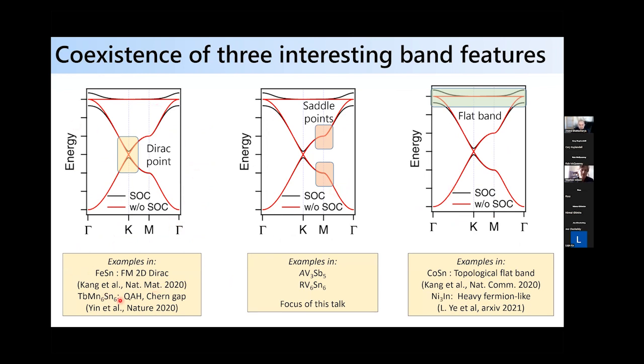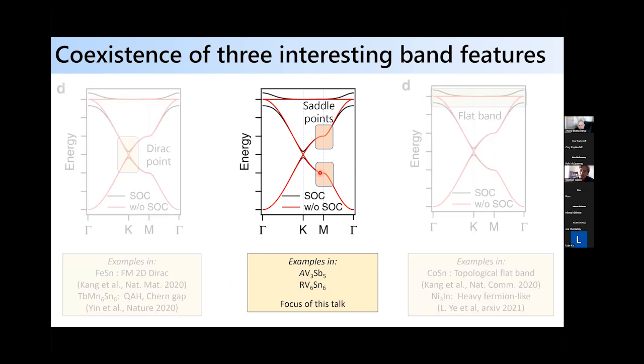So for instance, iron tin or these manganese-based 166 compounds exploit a lot of the phenomenology that comes from gapping out the Dirac points that are native to the kagome band structure. Joe Checkelsky's group has some beautiful recent work on Ni3In, looking at flat band physics, for instance, if you can tune the Fermi level towards the flat band in the kagome band structure. And these vanadium-based 166 compounds I was showing you nominally have fillings which are near the saddle points in their Fermi level. So this spurred some of our initial interest in these materials.